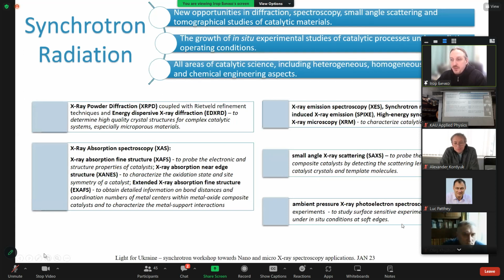And near ambient pressure X-ray photoelectron spectroscopy, a very useful method. However, the main disadvantage is that X-ray photoelectron spectroscopy, XPS, requires a high vacuum. So we cannot investigate our materials and our chemical processes in the conditions where these processes proceed in reality. So in XPS we need a pressure of about 0.1 millibars, whereas in heterogeneous catalysis typical pressures are from 1 atmosphere to 50. It can be even more, even 100 atmospheres and so on.